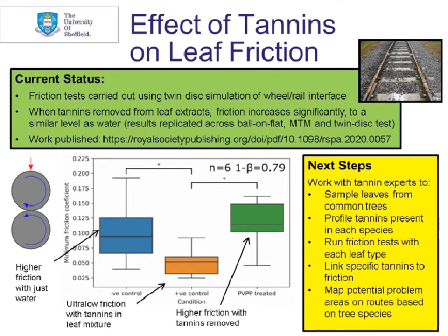So here we're kind of below 0.05, which is getting to the ultra low region, as would be defined for the wheel-rail interface. And then when we test with that same leaf tea mixture with the tannins removed, we get much higher levels of friction. So we're really starting to get to grips with the chemistry that's going on in the wheel-rail interface and understanding what those low friction mechanisms are. Obviously, understanding these will help people develop new mitigation methods that hopefully overcome those particular problems that we've identified.